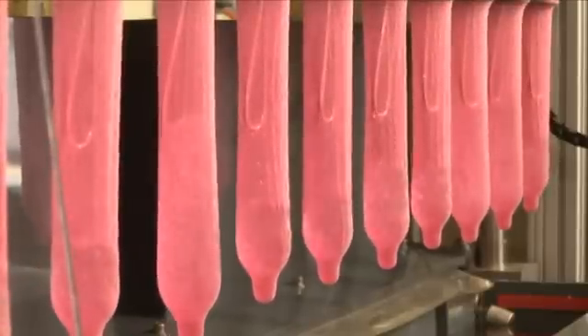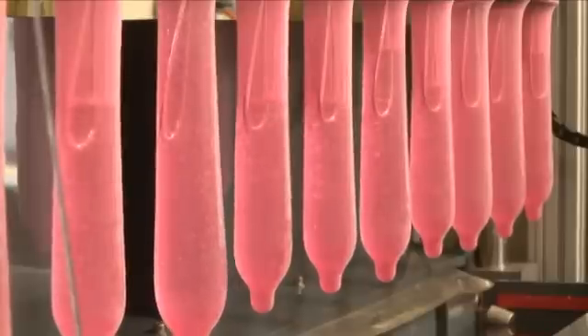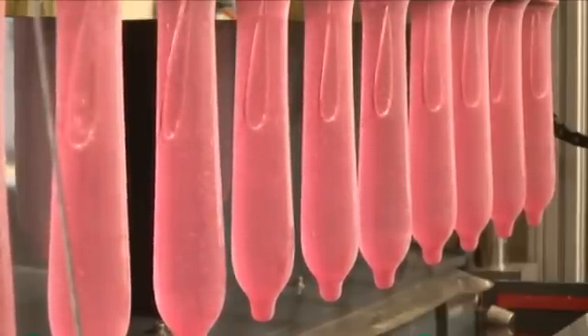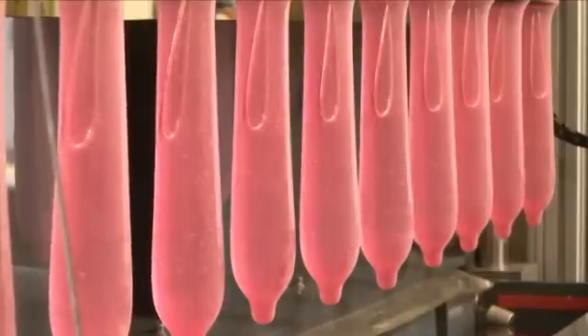Finally, another pinhole test completes this series of tests. This time, the condoms are placed over an electric conductor and filled with water. Then, they are immersed into a water-based solution to check whether any condom tested has a pinhole.